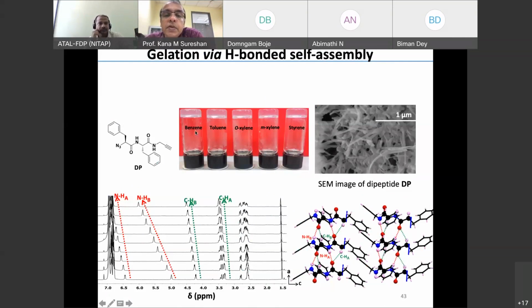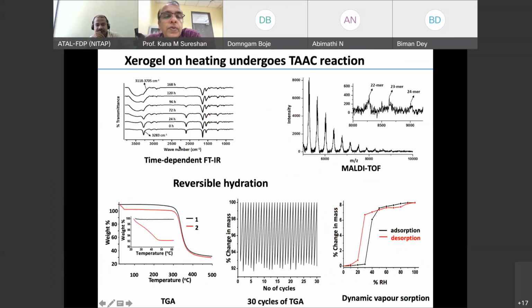It's a good gelator for many non-polar solvents. And this is the gel fiber. You can see an SEM image. And also you can see it's a hydrogen bonded network, as I have already told you for other sugar-based gelators. Now, this is the crystal structure, and in the crystal structure, these azide and alkyne from adjacent molecules are proximal for them to undergo reaction to form a polymer. So when you heat this gel, you see that this is completely reacted. This is a time-dependent IR spectrum. You can see the signature for azide slowly vanished because it's used in the reaction. It completely formed polymer. And one interesting thing you see here is there is something coming with the progress of reaction. Some water is coming. So that means it is taking water from the atmosphere during the reaction.